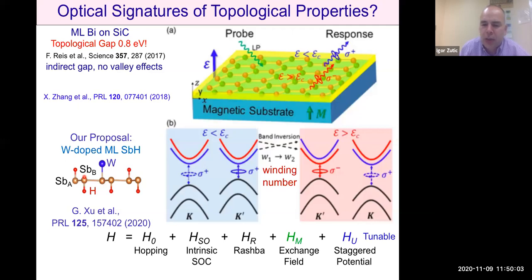Now something similar is happening with the winding number. If we can change the winding number, then one can argue that this changes the selection rule. And this winding number is one of the topological numbers that we argue could be tuned even in the same structure. We don't need to go to different thicknesses, to different samples. We can control it by gate, because staggered potential is also tunable by gate.